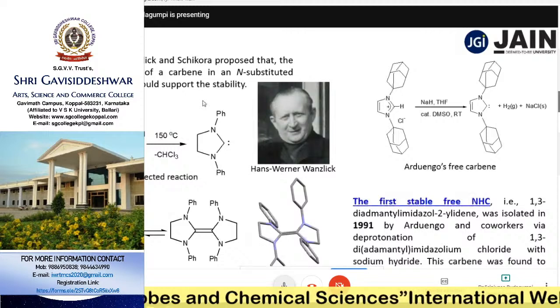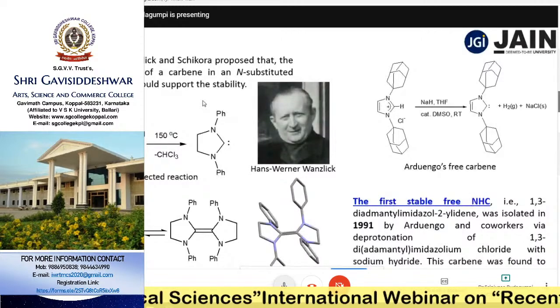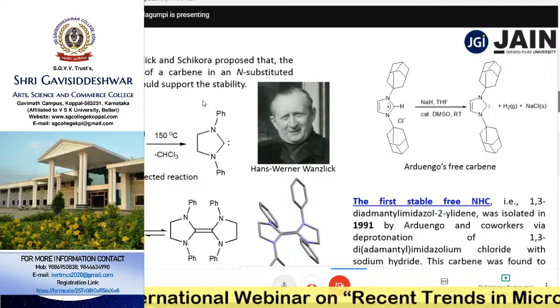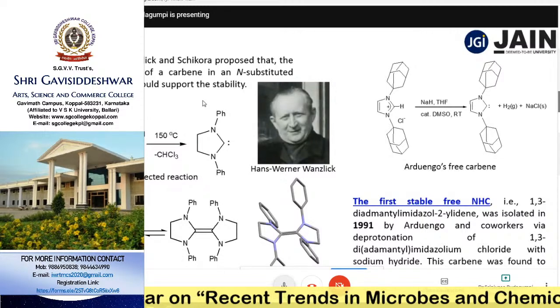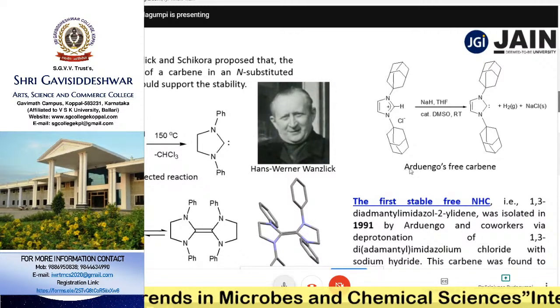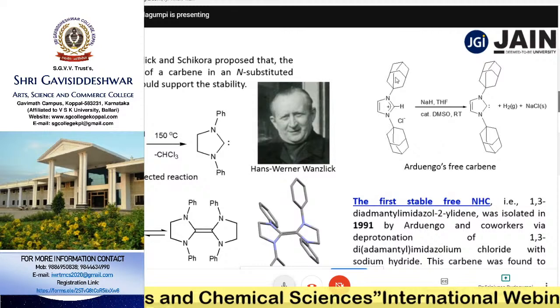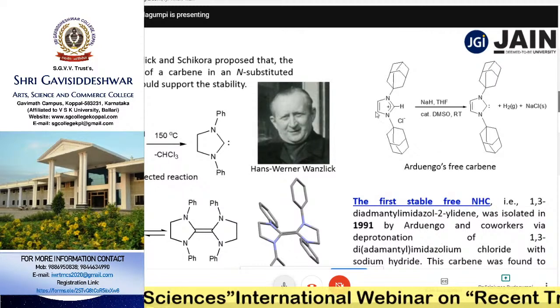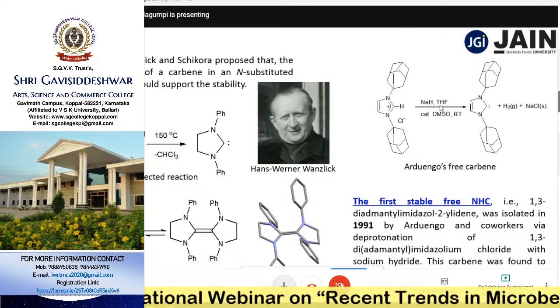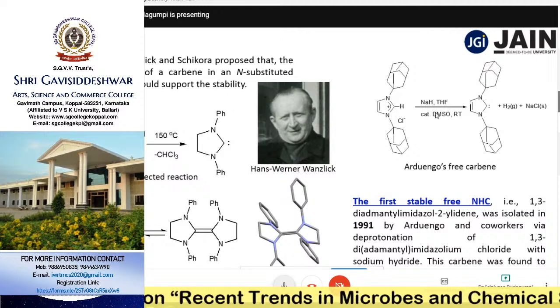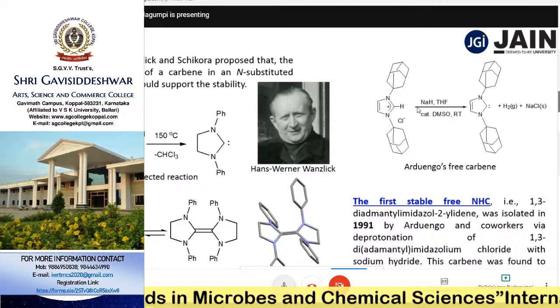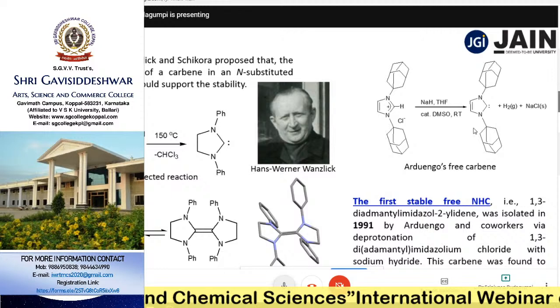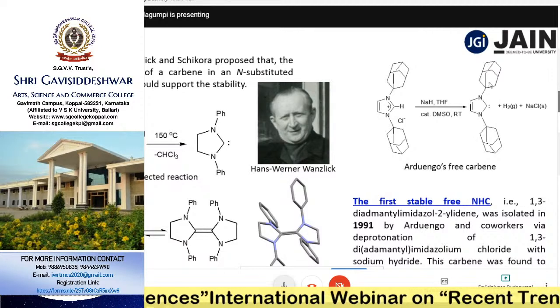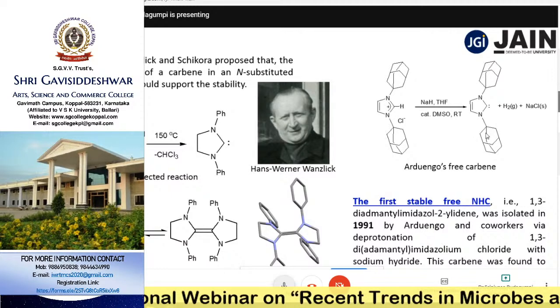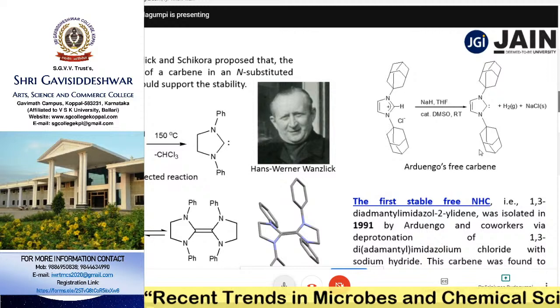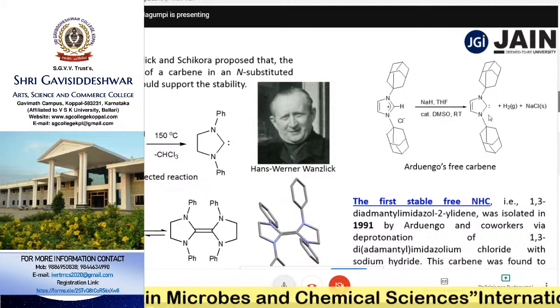Actually, NHC chemistry got born in 1991. So it is only around 30 years old chemistry. Now, in 1991, 1,3-diadamantyl imidazolium chloride was treated with a strong base such as sodium hydride in THF under catalytic conditions. Then they were able to isolate the free carbene, which is of course air and moisture sensitive. But still, the free carbene can be isolated.